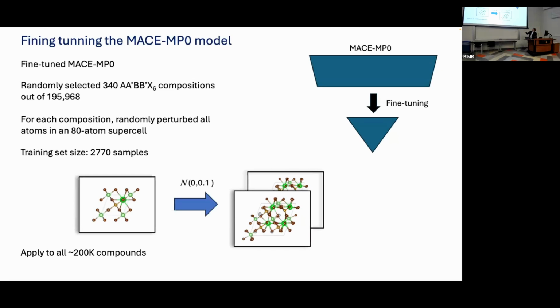We took these unit cells, we randomly perturbed them. So we displaced atoms, added some random noise to their positions, calculated the energies and forces in a large supercell of 80 atoms, and then added that back to the train set, and we fine-tuned to this data set. So a very narrow slice of the compositional space, extended slightly based on the atoms and forces that have been perturbed in the structure, and that leads to a data set of about 3,000 samples. So we took the MACE MP0 model, and we fine-tuned it to this data set.